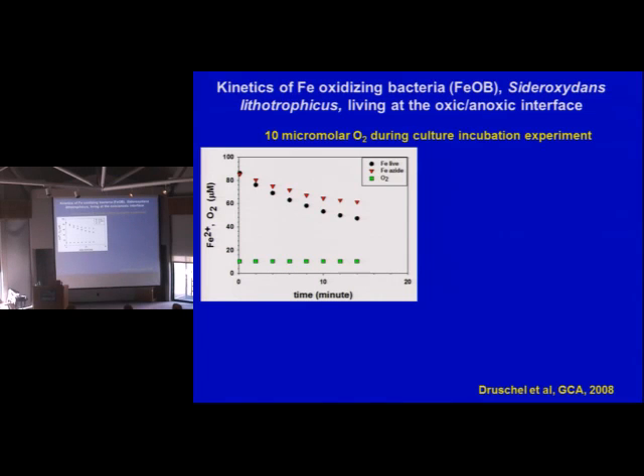Now, Greg Druschel, when he was in my lab, we tried to do things where he actually made about, in this case, about 10 micromolar oxygen right here. We're now going to do an experiment where we add the iron to, measure the oxygen and the iron. The red is iron in azide, and the black is iron live. So we do an experiment live, then we put in azide, do the experiment killed, and you can see a difference. Now, this doesn't have as much curvature as you normally would see in a pseudo first-order plot, but it's there. So we have the abiotic decay rate in red, because there's no biotic, and the black is the mixture of biotic and abiotic. And so we subtract the two to get these measurements. So you have to have exactly the right amount of cell counts to do this experiment. You can't have variable cell counts.